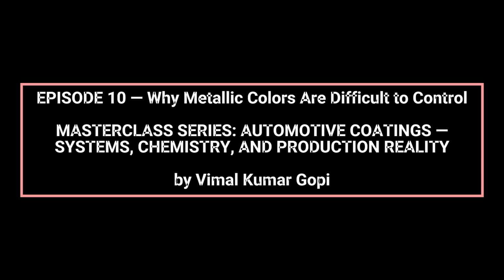For OEMs, metallic failures present as color mismatch between panels, poor flop consistency, stripe patterns, mottling, or unacceptable sparkle distribution. These defects are among the most common causes of color rejection during launch and early production. RD&I teams therefore design metallic systems not for perfect alignment under ideal conditions, but for controlled flake orientation across realistic production variability. This includes solvent robustness, rheology stability, pigment dispersion control, and tolerance to spray and flash-off fluctuations.